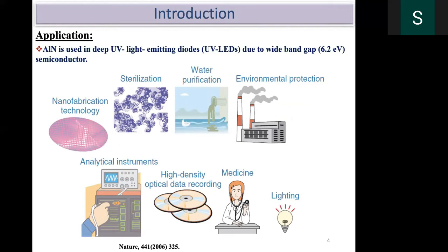DVD and these Blu-ray DVDs can be covered with a protective layer of around 98 nanometers, roughly. Those kind of layers can be cured with the help of this UV LED lights. And as I already heard from Professor Yuvraj, surface acoustic emission can be possible in the case of aluminum nitrides. And if you grow it in one single oriented direction, either C-axis or A-axis, it is possible. And in medicine also, this is a piezoelectric material. So this can be used as a very good ultrasonic sensor.